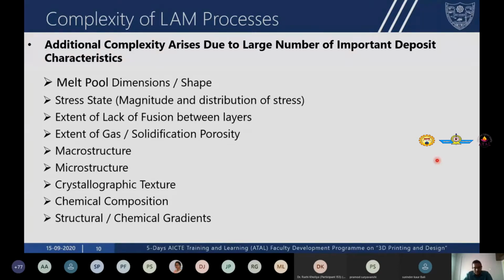Then what is the microstructure that's obtained? What is the macrostructure? Then the crystallographic texture of the components and the chemical composition. Many times the chemical composition of the powder and the chemical composition of the deposited part are going to be different because of the evaporation of the alloying elements. Then there are the structural and chemical gradients that will also cause the Marangoni effect in the melt pool.